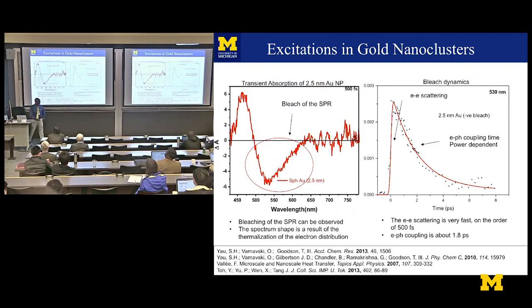Well, what does that mean? So here's the experiment, right? That's what I was saying. Here's where that surface plasmon was originally, and it got bleached. And then the wings move up a little bit. And then you can watch that process happen in time. This is the time in picoseconds. This is the change in absorption, the transient absorption. And the very fast initial process is related to some electron-electron scattering. And then the slow decay is related to this phonon coupling, meaning the lattice is moving.